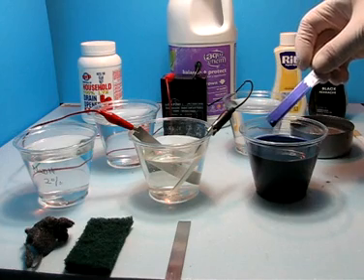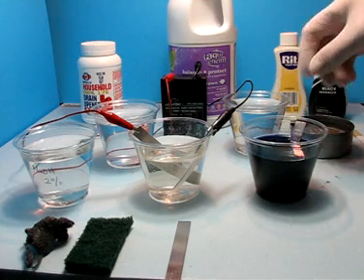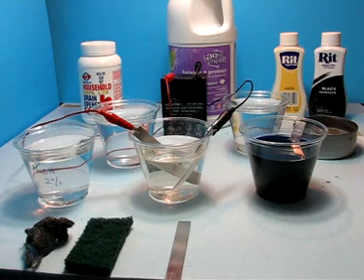Once the dye has reached the level of color that you want, you simply put it into a container of boiling water for 20 to 30 minutes. An optional sealing can also be done with nickel acetate, but I've found that boiling water is certainly a lot cheaper and does just as good a job sealing the dye into those cell structures.